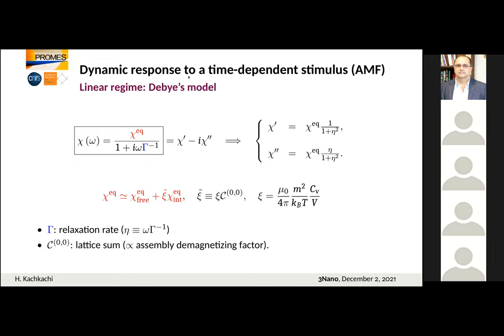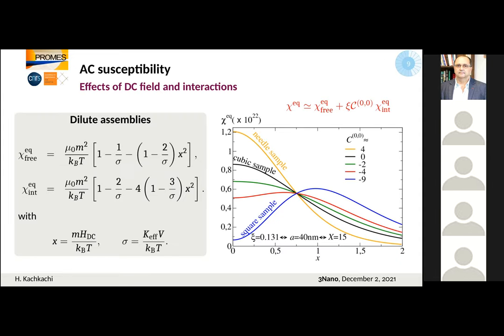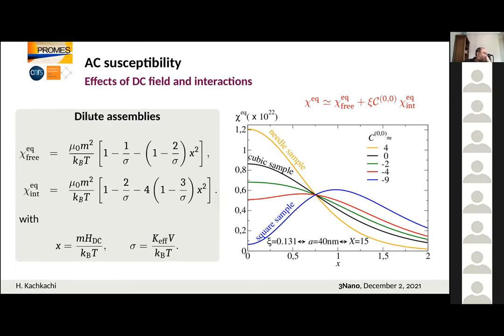So in brief, to summarize, in the susceptibility we need properties pertaining to the assembly: organization and concentration, which is CV here. Of course, we need temperature. We need the magnetic field, as we will see, because we need to compute the equilibrium susceptibility and the relaxation rate. Without going into those details, take an example of dilute assemblies, meaning the interparticle distance is larger than roughly 3 times the diameter of a nanoparticle. We have a part here for free particles with no interactions, and this part is the contribution from interactions. So we can compute both contributions: for free, isolated or very dilute nanoparticles, and the contribution from interactions.